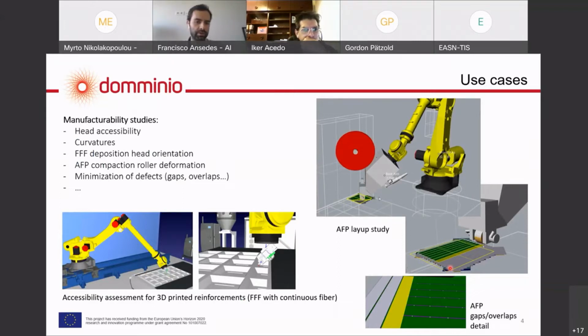Also the position and head orientation in order to have good trajectories, and the compaction roller of the AFP, which will have a lot of importance in order to transmit good pressure to the part. And also minimization of other defects that can arise from the previous aspects, such as gaps, overlaps, and any surface defect that we can have here.